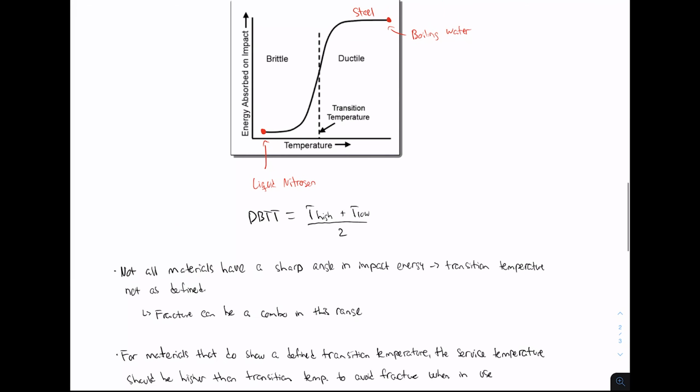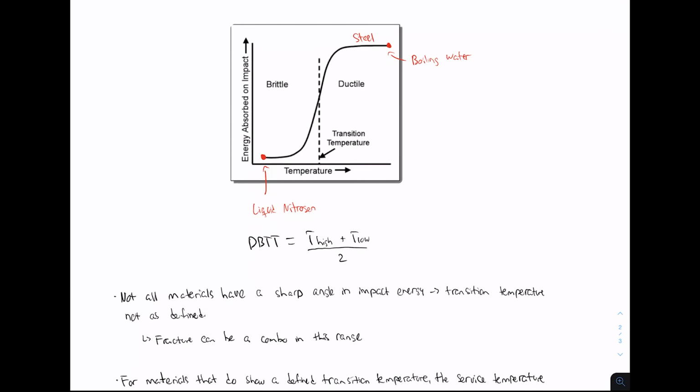Okay, so the last thing would be to talk about the fracture appearance. But again, we talked about that earlier on, and we showed examples in the pictures. But to reiterate, if you have a ductile fracture mode, you're going to have kind of jagged edges. It's not going to be smooth. It's going to kind of look like the material was pulled, and that's because it's absorbing more energy. So it takes a longer time to fracture, essentially, because it's going under more strain.